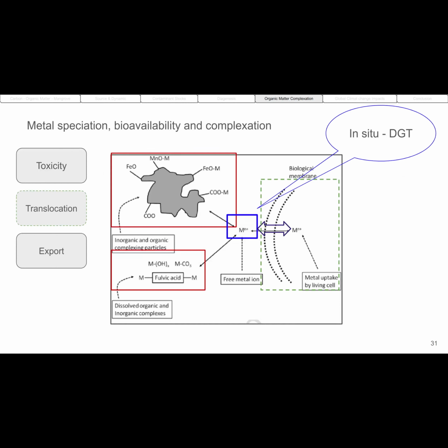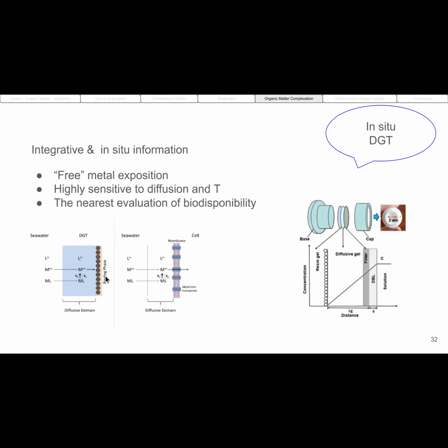Another technique is to use the DGT. DGT is very interesting because technically it's the technique that allows you to measure only the free metal ions. I don't know if you know this technique, but in fact it's a thin diffusive film. You have a resin and you have a gel here and the filter, and only the free metal can reach the resin. So technically it's the nearest technique to bioavailability, because we can consider that the gel and filter act as the cell wall.